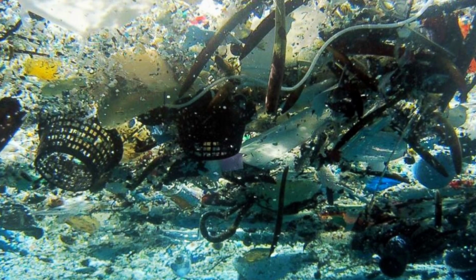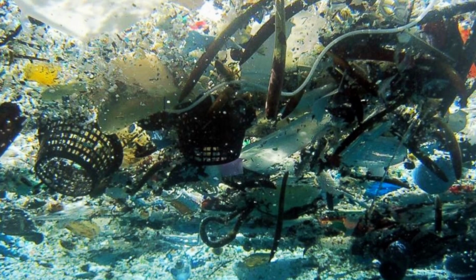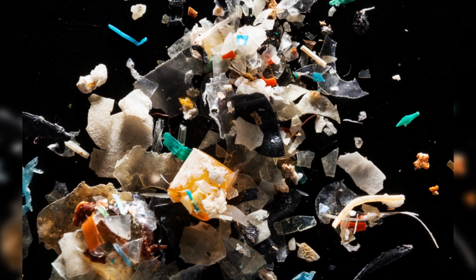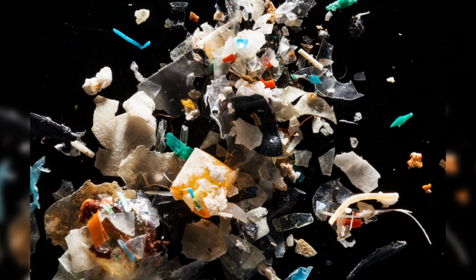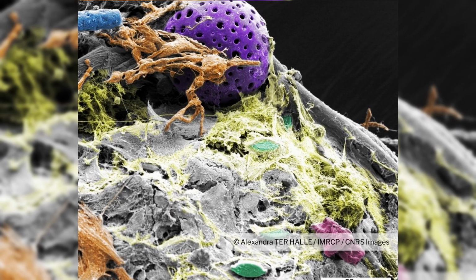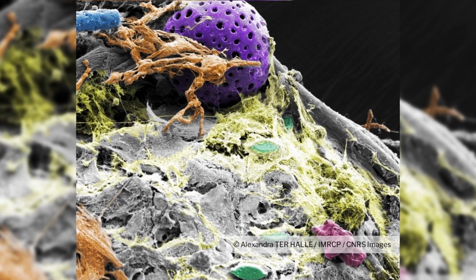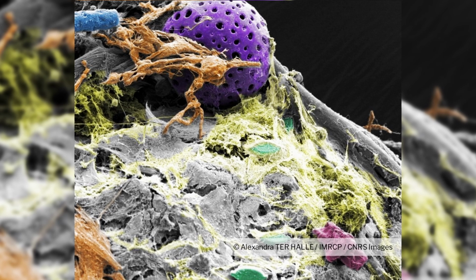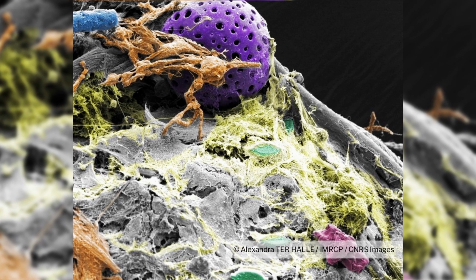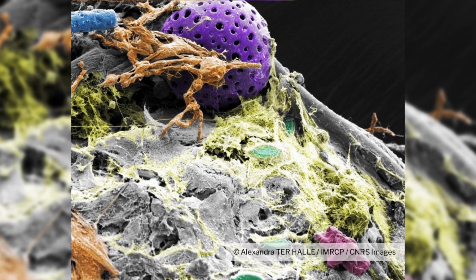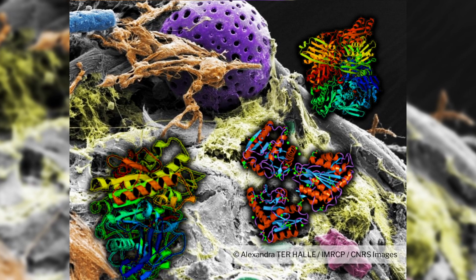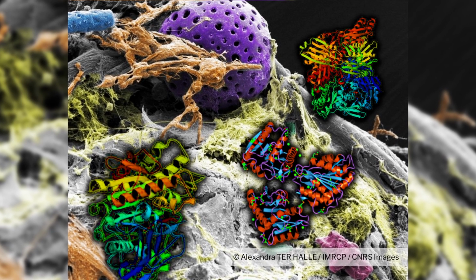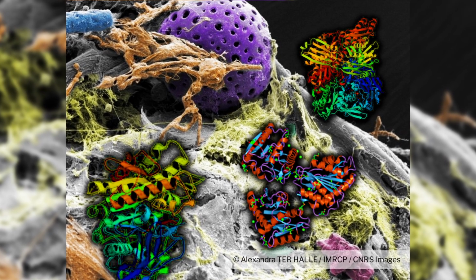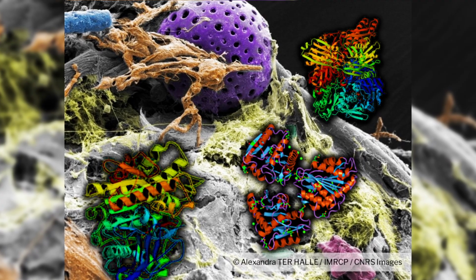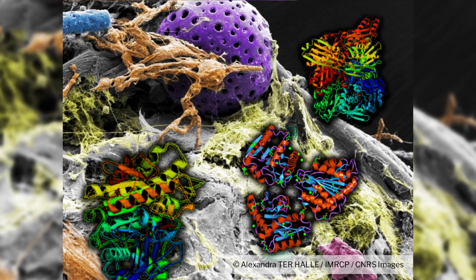Because individual microbes often fail in real-world conditions. But in the plastisphere, degradation is amplified by cooperation. One species can initiate oxidation of the polymer. Another can hydrolyze the resulting fragments. The microbial diversity increases the range of enzymes present: oxidases, hydrolases, esterases, enabling a broader attack on the plastic surface.